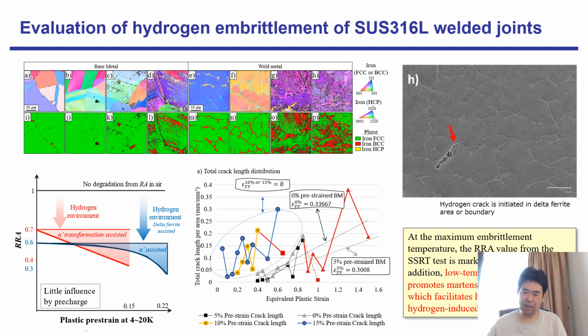We think this has to be related with martensite transformation, because this is an EBSD image: virgin, 0% pre-strain, and 5%, 10% and 15%. So clearly 10% is the starting point of martensite transformation. This is the starting point of the crack formation, and this degradation is probably related to martensite transformation.